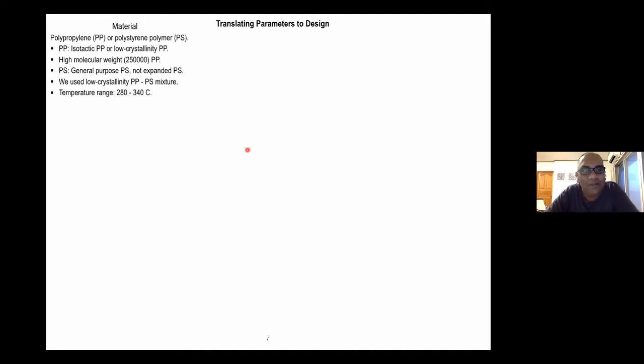So let me go through this boring part, because this was where 99% perspiration, as Edison would have said, went in, trying to tweak and figure out the parameter ranges. So we used polypropylene or a polypropylene polystyrene mixture, and the temperature range, which I figured from the previous reference, was 280 to 340 degrees Celsius. For jet initiation, from simple calculation, the threshold angular velocity should be around 4,500 RPM, revolutions per minute. But I was seeing fibers being generated at 2,450 RPM. So you should take those two expressions I showed in the earlier slide as ballpark, order of magnitude estimates.